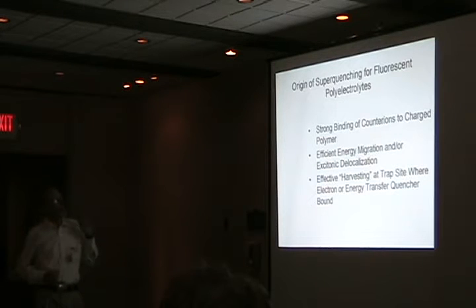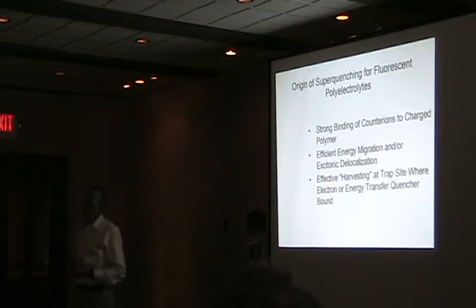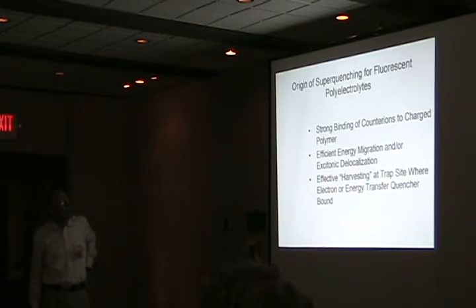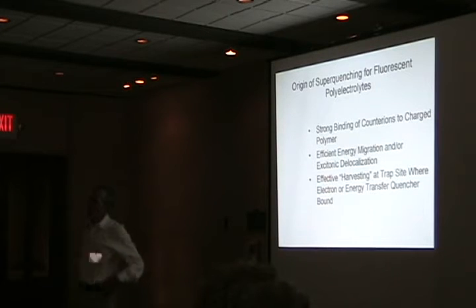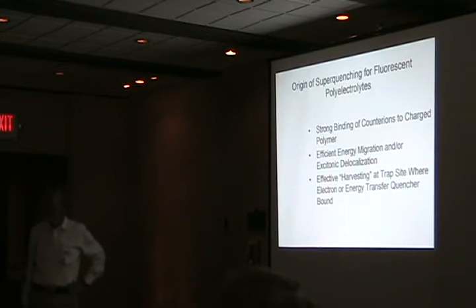Well, we've actually tried to separate out what we attribute that high rate constant for quenching, or Stern-Volmer constant, to. For example, about 10 to the 7th is due to the strong association. And then we would say somewhere around 10 to the 2nd is due to the delocalization.